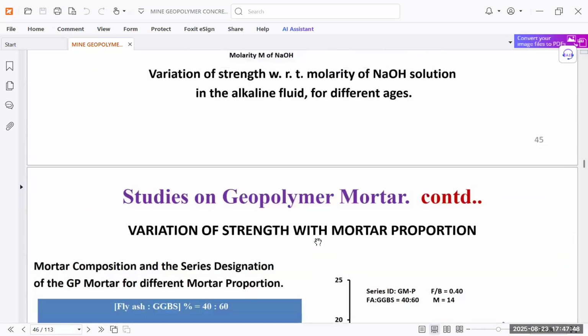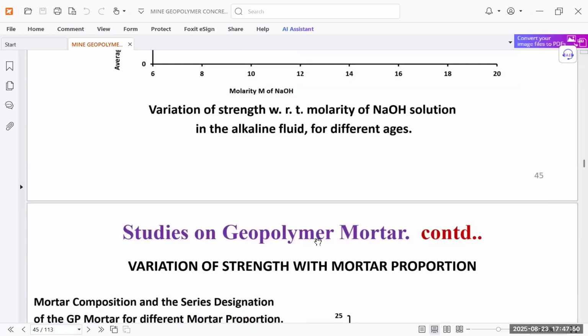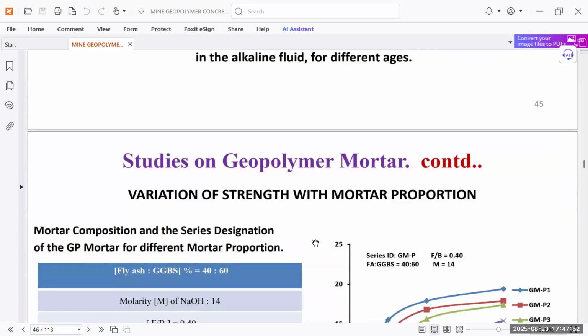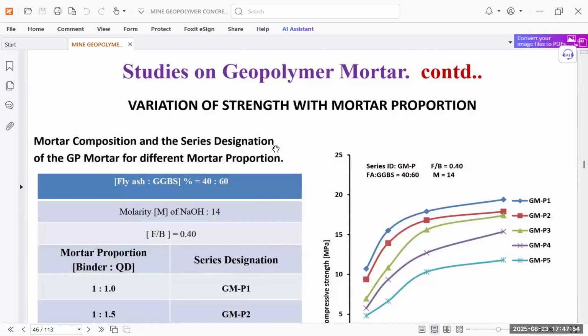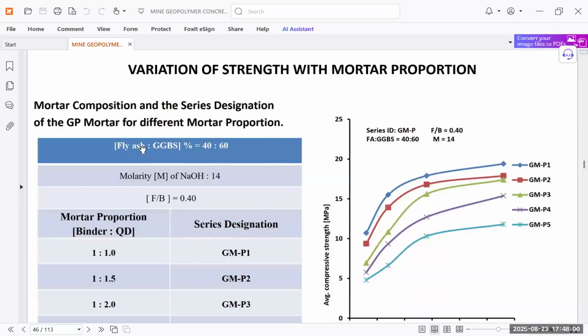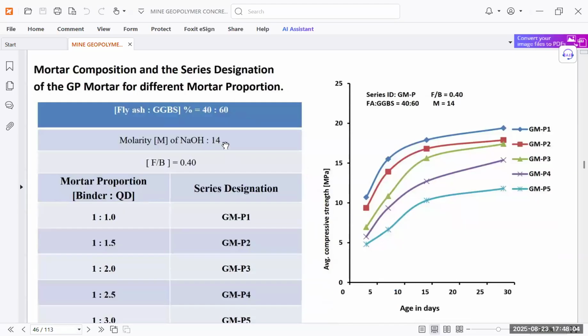So further studies on geopolymer mortar have been done. The variation of strength with mortar proportions is shown. Mortar composition and series designation of GP mortar for different mortar proportions we have done. Here the fly ash to GGBS ratio is 40 to 60, the molarity of NaOH is 14, and the fluid to binder ratio is 0.4.